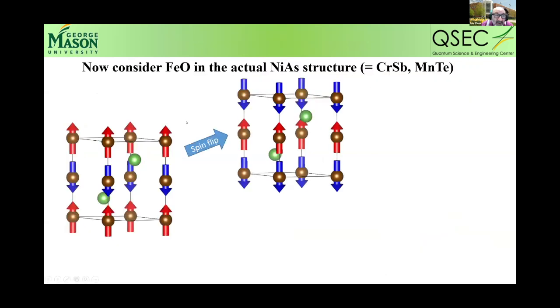But now let's consider iron oxide in the actual nickel arsenide structure. And there are magnets that crystallize in this structure, like chromium antimonide or manganese telluride. Now, it's exactly the same structure, but now my non-magnetic atoms are those atoms which are related by inversion symmetry. But the inversion center here, which is right in between, actually maps one iron spin upon itself.